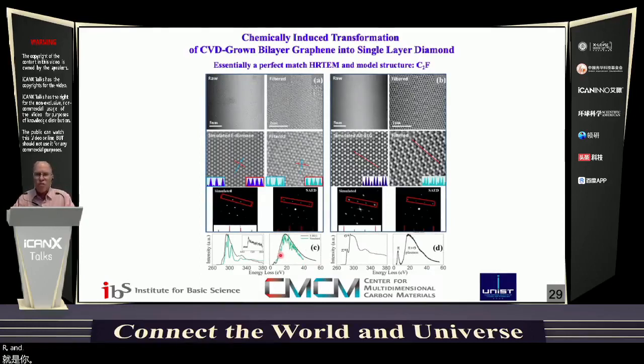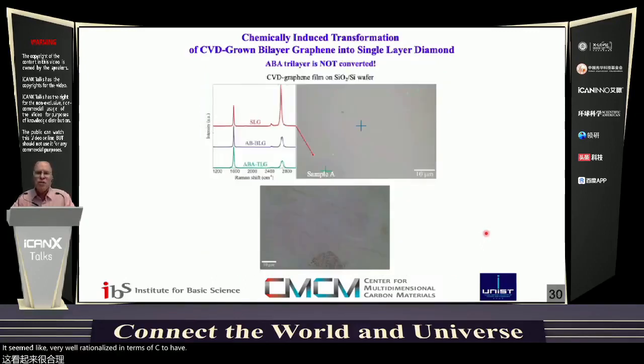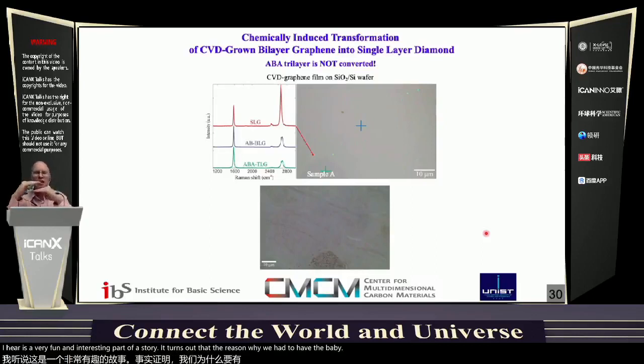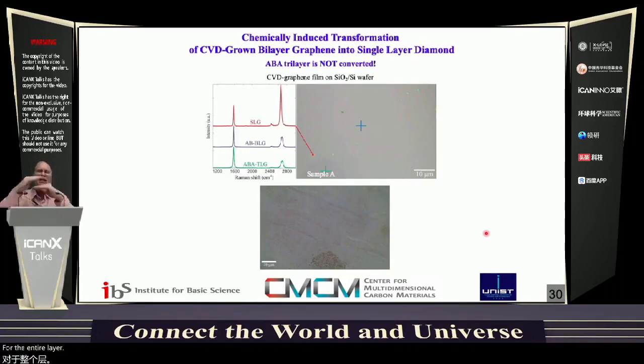And through the calculated spectra in comparison with the experimental spectra, it seemed very well rationalized in terms of the C2F structure. Now, here's a very fun and interesting part of the story. It turns out that the reason we had to have the AB stacking in the first place is we need the carbon atoms to be pretty much in the right places for the interlayer bonding to develop once we start fluorinating the top and bottom surfaces.